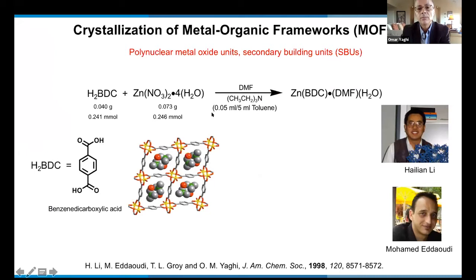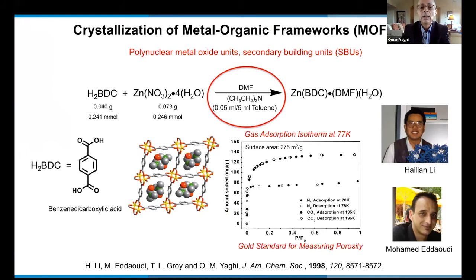It's made in DMF with base to deprotonate the acid and then crystallized. So these conditions are sort of magical conditions that we have come up with that are being used until today to make MOFs.